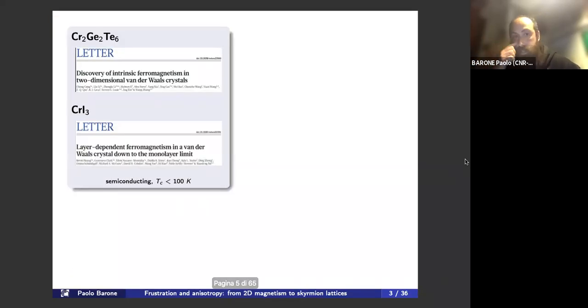And we have seen already yesterday that the prototypical examples of such materials are this chromium-based triiodide and this telluride, which are both semiconducting van der Waals crystals. In the bulk form, they are both ferromagnetic with a critical temperature of about 60, 70 Kelvin. In both cases, they were able to show, especially for chromium triiodide, that it could maintain a relatively high critical temperature, even in the monolayer limit. And this was explained actually in terms of Ising ferromagnetism.